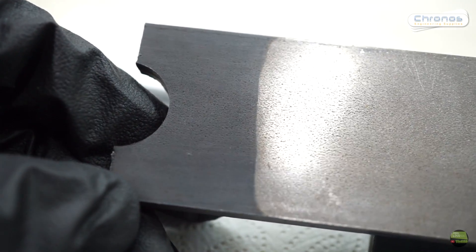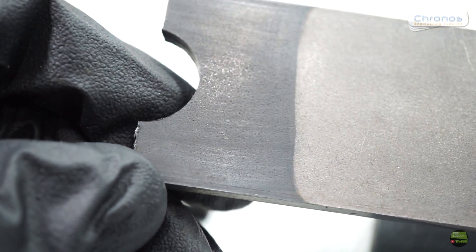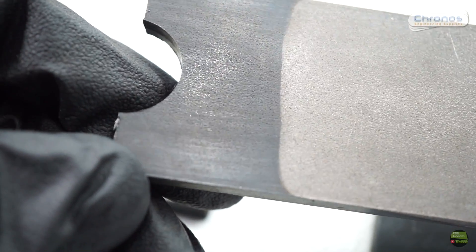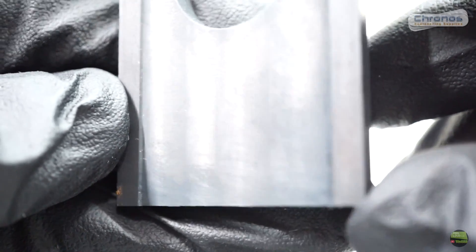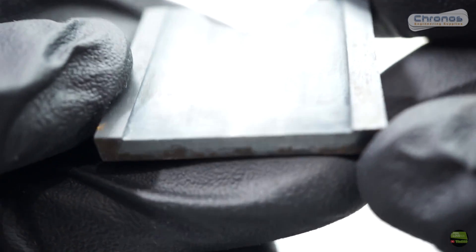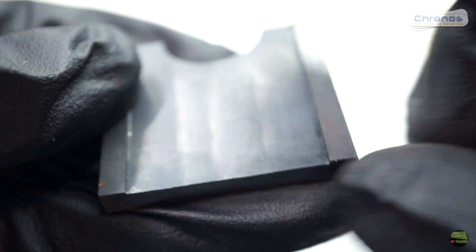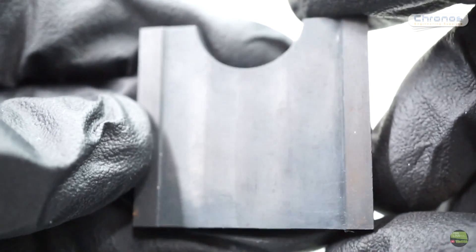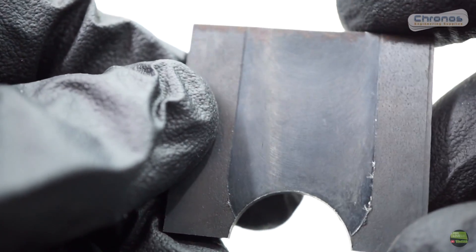And that's the result. On that raw piece of steel is still protective oil. We can see that where the part is black it doesn't shine anymore. The other part is a bit milled, oiled and rusted. On the milled area we got very nice evenly blacked surface. On the oiled part from the side it's a bit more shiny and the black isn't that deep. And the rust is still there, just a bit less visible.